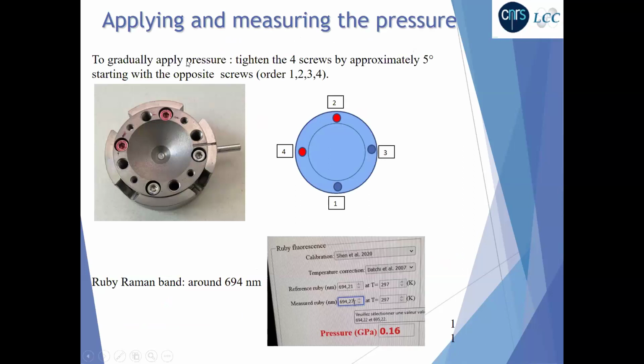To gradually apply pressure, it is recommended to tighten the four screws by approximately 5 degrees, starting by the opposite screw, 1, 2, 3, 4. As I mentioned before, we use the ruby fluorescence to determine the applied pressure. Before applying any pressure, we first determine the fluorescence of our reference ruby at ambient pressure.